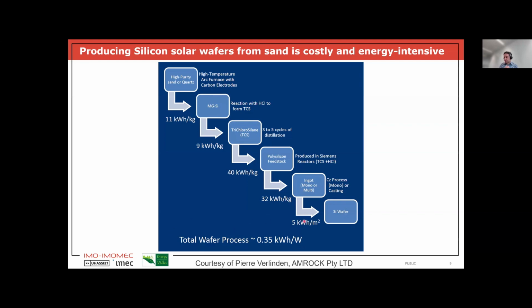So in total, we have a lot of high temperature steps, a lot of energy that is needed. And we estimate that you need around 0.35 kilowatt hours per watt peak that your wafer will produce. So it's quite a lot of energy, and that explains why it's also quite expensive in the end to make these wafers, and they are responsible for 40% of the total module cost.